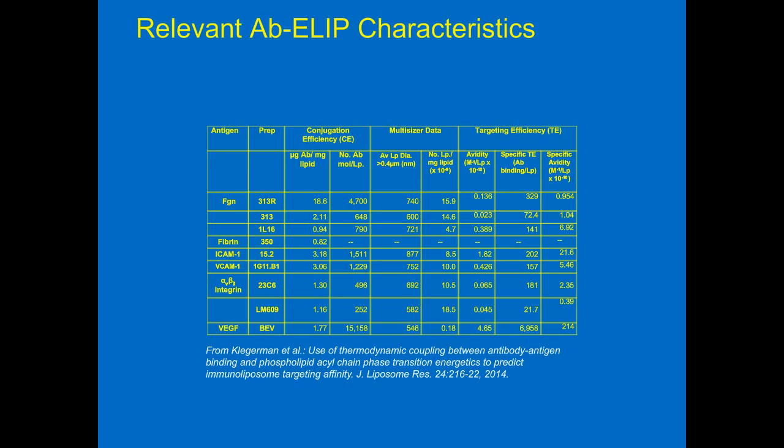We typically use liposomes that are conjugated to non-specific IgG as controls. So these are fully echogenic, but they're not specifically targeted. However, they do have protein on them. And then you find relative to that, for instance, for ICAM1 targeting, we often find a 40% enhancement of